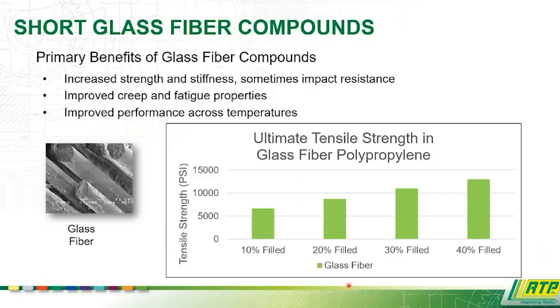So if we take a look at this graph, as we add glass fiber to, for example, polypropylene here from 10, 20, 30, 40%, you'll get a rather linear increase in your tensile strength. And that's going to be true for most polymers. There usually is diminishing returns around 50% for tensile strength. Your modulus will continue to improve as you add more glass fiber, with the limits usually being somewhere around 50 to 60% maximum loading. The downside of adding glass fiber is your specific gravity or density does go up.